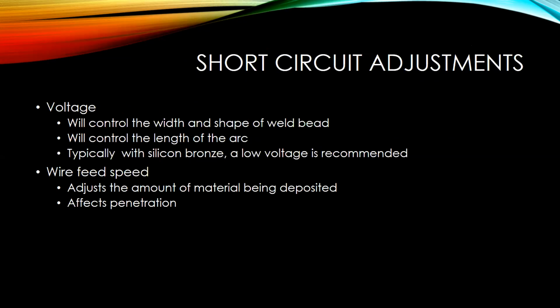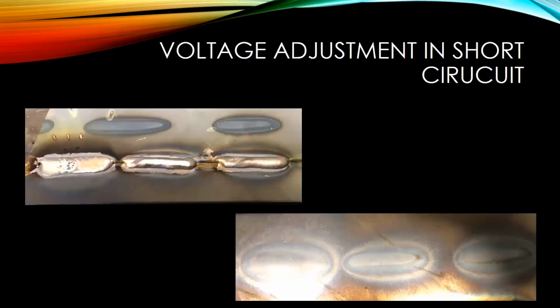So let's dive a little bit more into the short circuit adjustments. Voltage will control the width and the shape of the weld bead. It'll also control the arc length. As we were talking about before, once we start getting into a high voltage, that'll change our transfer and change our arc length. Typically what you'll see with silicon bronze though is a really low voltage is used versus a solid steel wire. For wire feed speed, it'll adjust the amount of material being deposited, and it'll also affect your penetration.